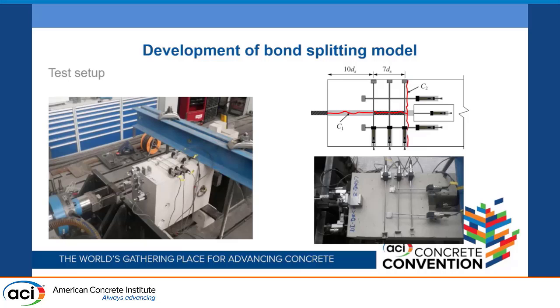We see the instrumentation. We wanted to measure the crack width, so we anticipate a crack width parallel to the rebar and perpendicular to the rebar. So if there is a crack coming perpendicular to the rebar, then to avoid the concrete cone breakout of the specimen, we had provided the longitudinal reinforcement, which would take up the forces once this crack comes, and eventually it will always fail in the splitting.